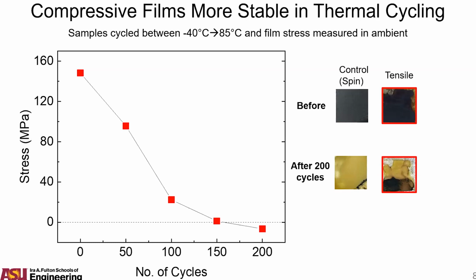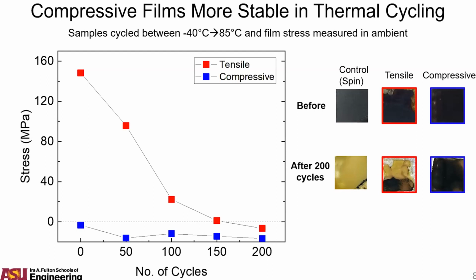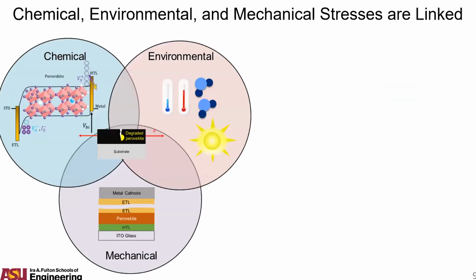And through engineering in compression, through processing, and we add these polymer additives, we can actually create compression initially, and then they withstand these thermal cycles very effectively, and it retains its dark structure and remains operational after 200 cycles. And so we're just at the beginning of wanting to explore this in more detail and study the interaction between space conditions such as these temperature cycles, but also things like radiation, and then effects ultimately on the mechanical properties, so that we can design a robust and reliable system.